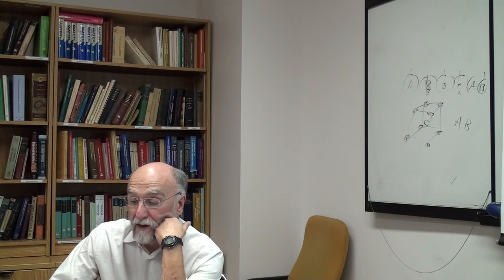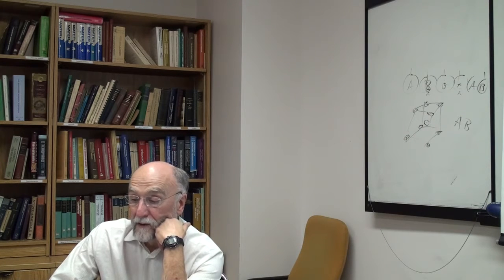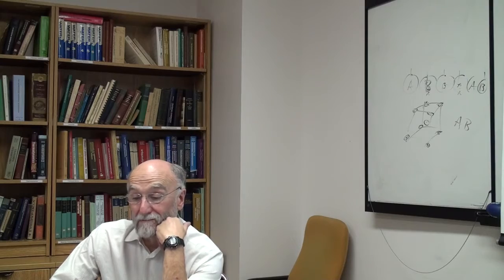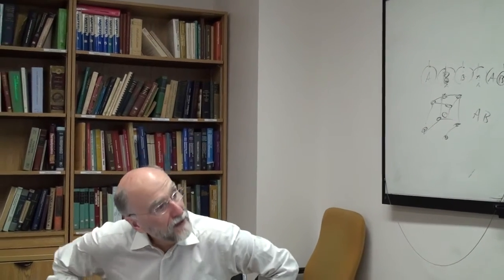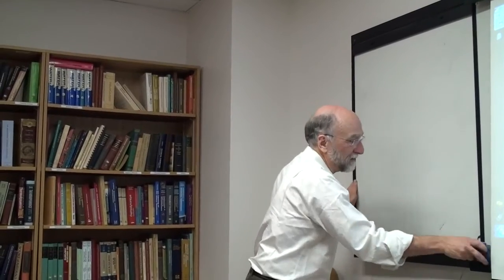Now the whole theory of sublattices can cause a little confusion, but I'm going to present the thing this way because this is how it was actually developed. The whole theory of sublattices clearly cannot apply to a liquid. A liquid cannot have long range order, obviously. But some liquids have so much short range order that for all intents and purposes, for modeling purposes, we can treat them as having 2 sublattices. It's so much simpler to treat them as having 2 sublattices.